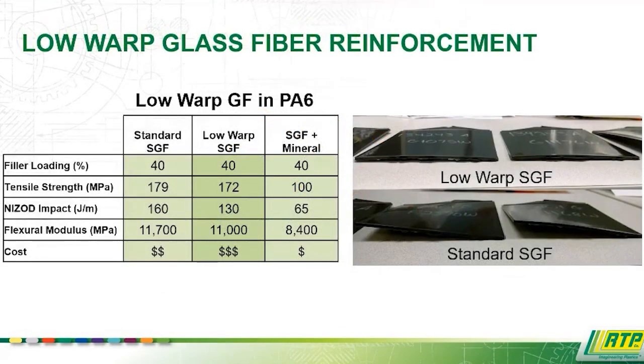A little different approach is our low warp glass fiber reinforcement. And that's really useful for when you can't sacrifice the properties that you lose when you combine a mineral. So for example, here's mineral filled nylon 6s, 40% standard glass fiber. You're going to have a tensile strength around 179, but if you move to a mineral combination, you're going to lose quite a bit of that. Same with the stiffness. What we can do is introduce this low warp short glass fiber and maintain most of those properties and still improve the dimensional stability.